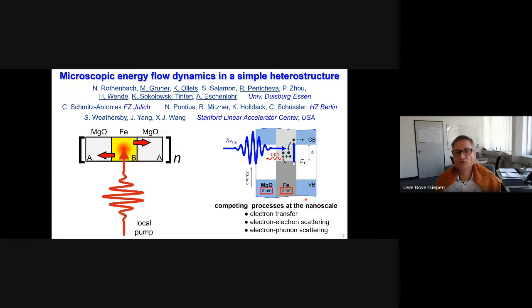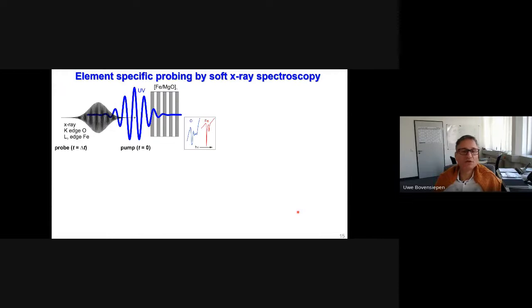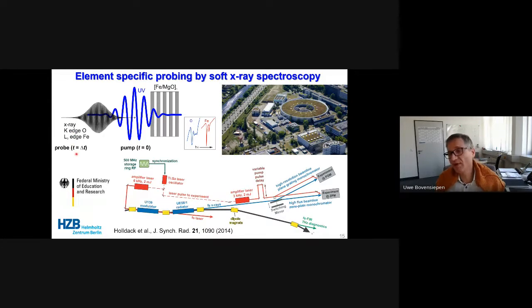These are very thin layers of only 2 nanometers, and we have several in a row in order to perform transmission experiments in this heterostructure. And we do transmission experiments using soft X-ray spectroscopy, and soft X-ray spectroscopy allows us to probe the oxygen K edge. So here you see the transmitted intensity for the oxygen K edge that represents the insulator, and the iron L3 and L2 edges to represent iron. And with this kind of an experiment in transmission, we can use the UV as a pump and the soft X-ray at the representative absorption energies to investigate the dynamics in the insulator and in iron. Now, this is something that we do not yet have tabletop, but I will show you that we are on a good way to get there.